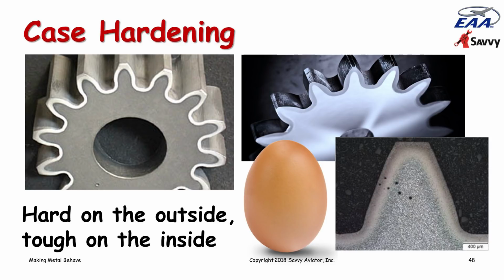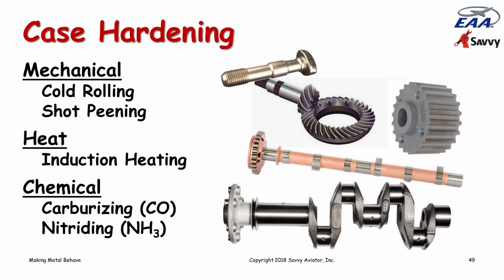And there are a number of different ways to do it. We've already mentioned some of them. We can harden the surface of a material by rolling or shot peening. We can heat treat just the surface of the metal by using induction heating, where the material goes inside of some coils and some high energy AC is applied to them that heats up the very outside. Or we can use chemical case hardening. And most crankshafts and camshafts are case hardened chemically. Most camshafts are hardened using a process called carburizing.